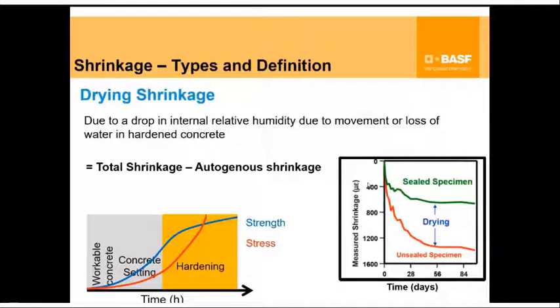So imagine the level of the stress that needs to come through in order to get the cracks. The stress level has to be really high to overcome the strength that the concrete has already gained over 28 days, which means when cracks form at 28 days due to drying shrinkage, those are big cracks, those are deep cracks. The plastic shrinkage cracks are most likely on the surface, and they are mostly non-structural. These ones could be the dangerous ones to look out for.